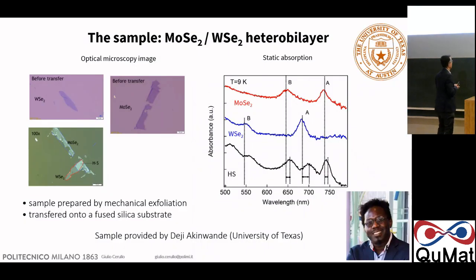The sample was provided by Deji Akinwande at the University of Texas. Here you see, maybe you cannot see the scale, I think it is 10 microns. So these are really small flakes on the order of 10, 20 micron, and they are mechanically stacked on top of each other. And there is an area where there is only the WSe2, an area where there is only the MoSe2, and an area where you have the heterostructure.